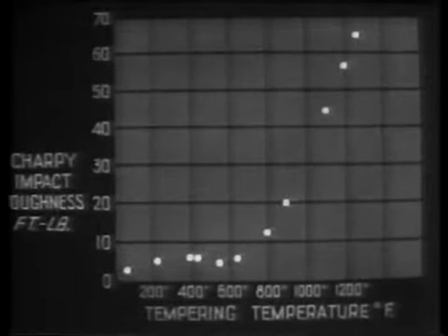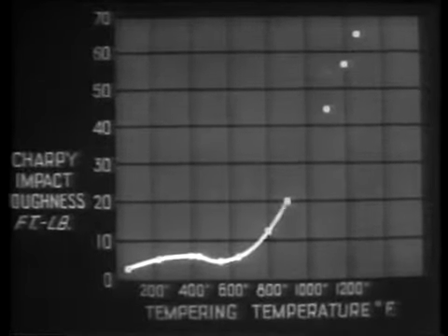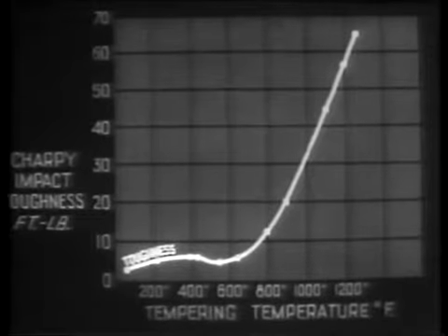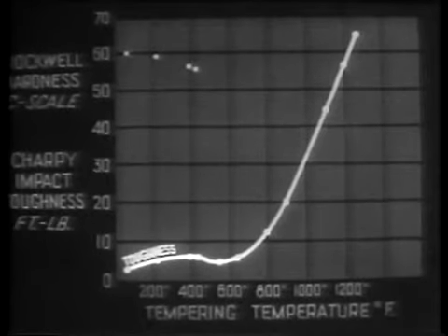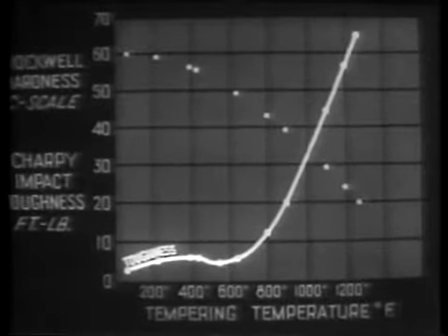From these and additional test data, a graph can be made to illustrate the relation between the toughening of the steel and the accompanying change in its hardness. As abscissa, we have the tempering temperatures in degrees Fahrenheit. As ordinates, we have the Charpy impact toughness in foot-pounds. We plot the values obtained by testing our steel after tempering at progressively higher temperatures. These points give us this curve. Now we also plot as ordinates the hardness readings of the steel at the same tempering stages and obtain this curve.